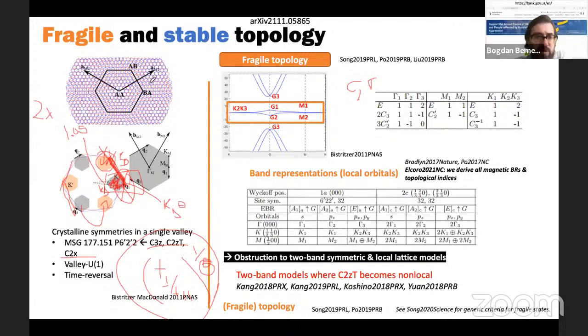That's a very good question. You don't. So these angles do not need to be commensurate. Commensuration of the lattice happens at some angles. Now, of course, I can get very close to any commensuration, but this is a continuum model and it's an emergent translational symmetry. So you don't have to assume commensuration of the lattice. The remarkable thing is if you just take two layers of graphene and twist them a little bit, at a random angle, you'll see a new pattern, even though you haven't hit an exact commensuration.